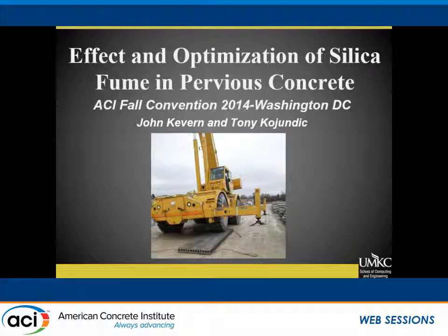And so they came to us and said, well, can we put together a study that looks at the effective dosage rate. So what I'm showing here is we've done a whole bunch of precast pervious concrete pavement sections or sidewalk sections for the city of Milwaukee. And this is a hollow core 6-inch pervious concrete precast section that has silica fume in it, and this is our very technical field loading test. So as long as you've got really good subgrade, it has pretty good performance.